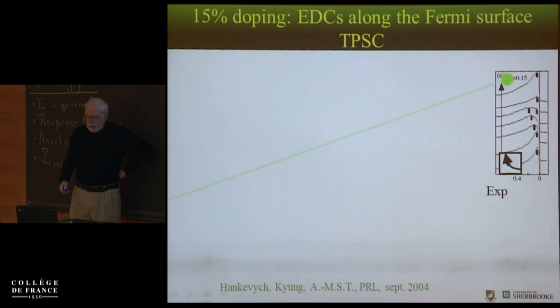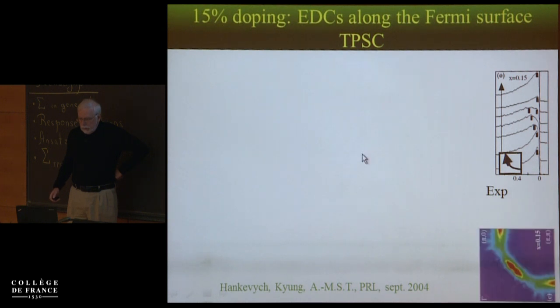So these are the results of experiment. So this is the ARPES spectrum for different wave vectors. So we move along the Fermi surface, and we have 15% doping. So these are energy distribution curves. So, for example, the Fermi level is here at omega equals 0. This axis is frequency. So this peak here corresponds to this place. So there's a peak because there's weight near the Fermi energy. Here you are at pi over 2, and again there's weight because there's a peak near the Fermi energy.